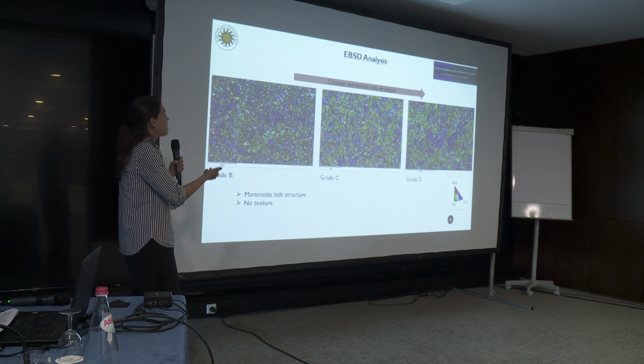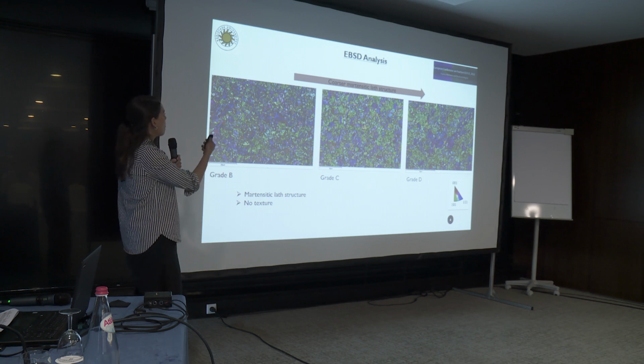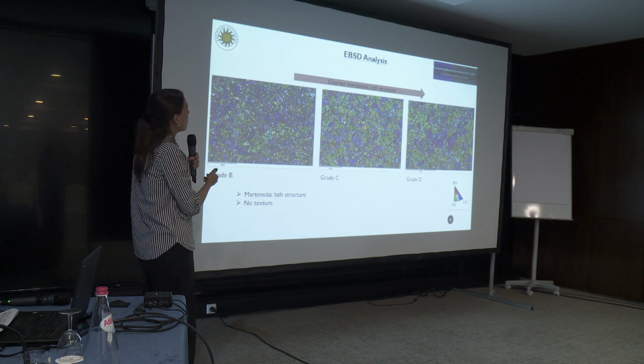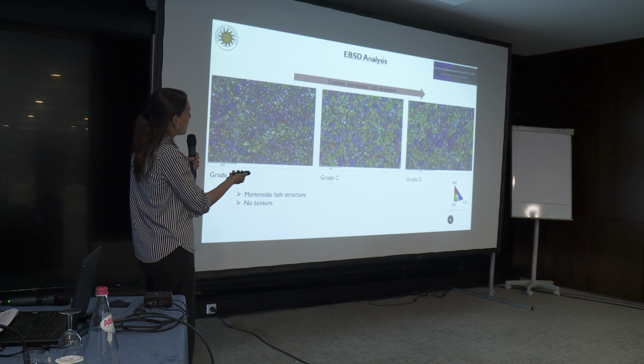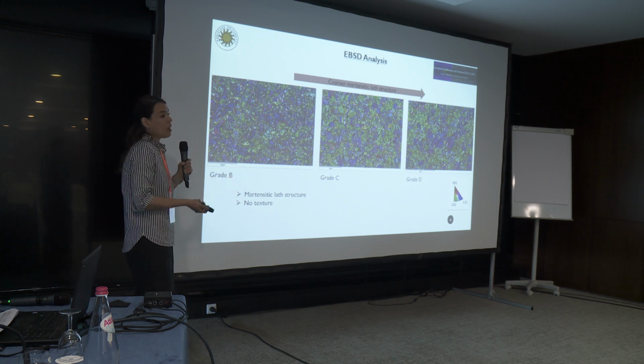We did the EBSD analysis in order to have some information about the main microstructural features. We have a martensitic lath structure. As we go from grade B to grade D, we are going from a fine to a coarser martensitic lath structure, and we don't have a strong texture.